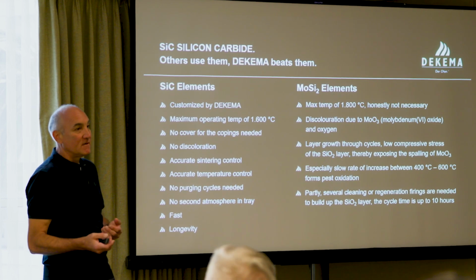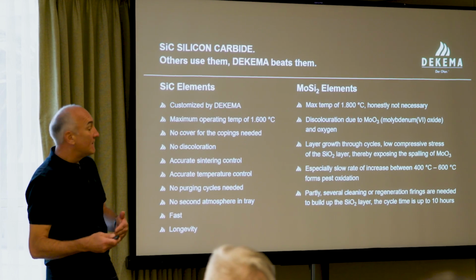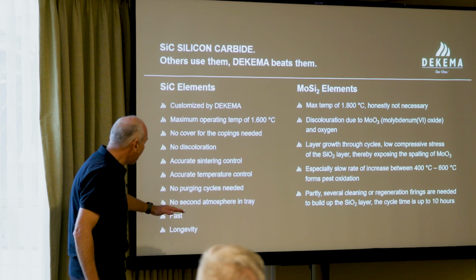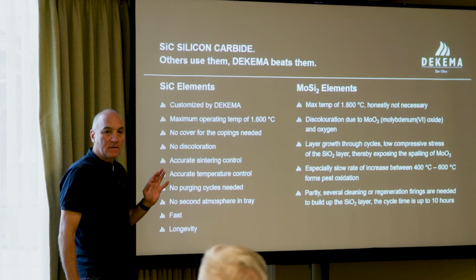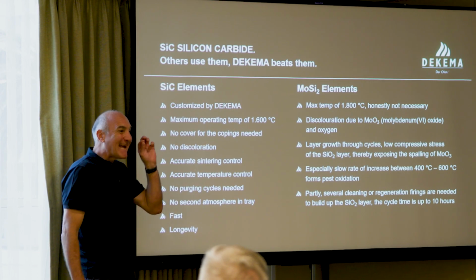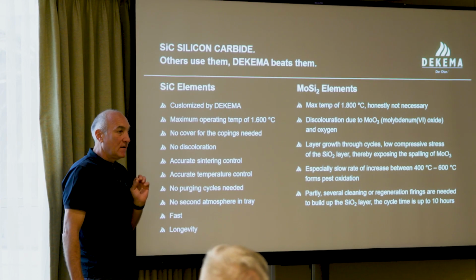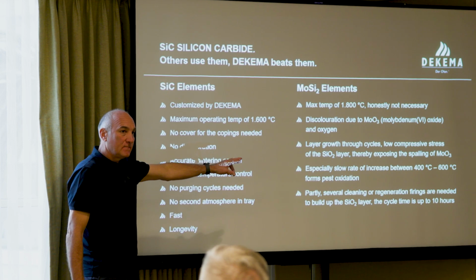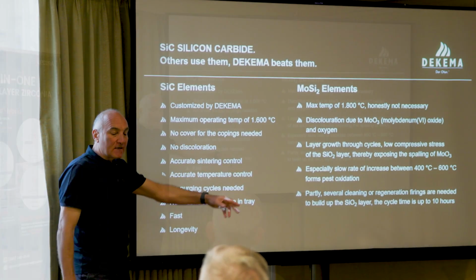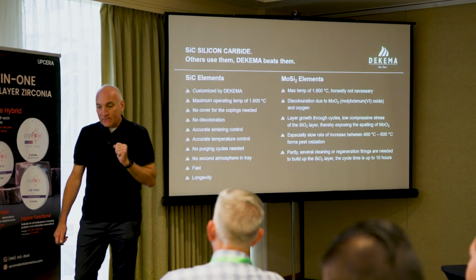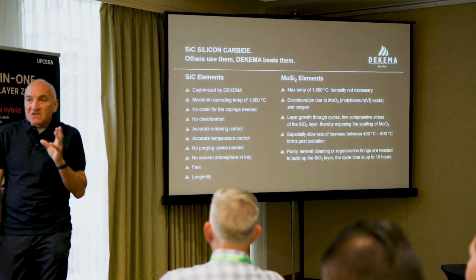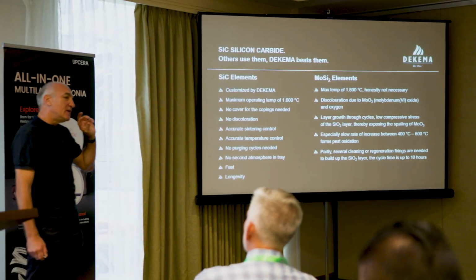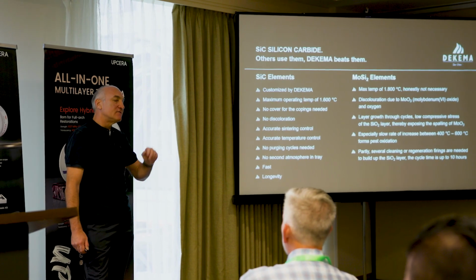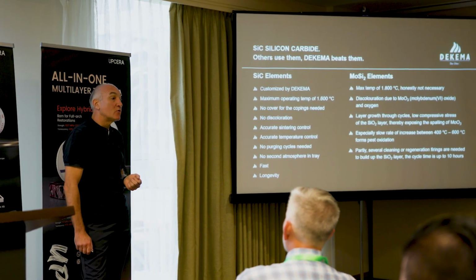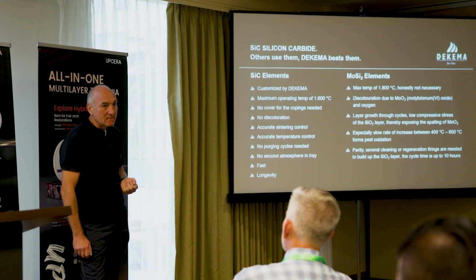Now everybody talks about zirconia in less than 1 hour or even less than half an hour. So fast. This material can be stressed. We don't talk about lifetime. We talk about cycles. And this is what you even should do with these. When I talk about a 10-hour cycle, we currently would suggest to exchange the heating elements every 700 cycles. So we talk about 7,000 hours.